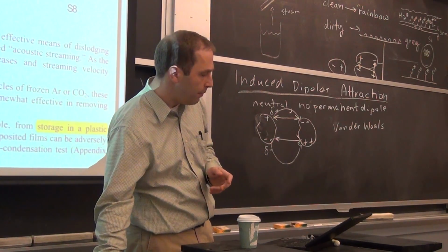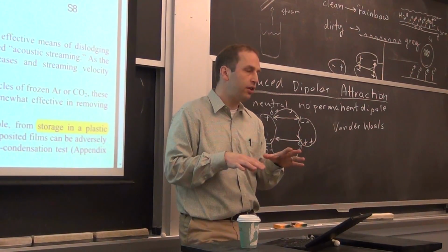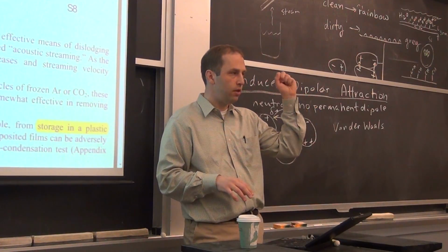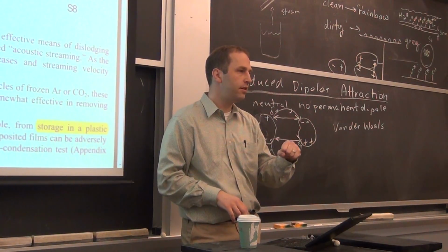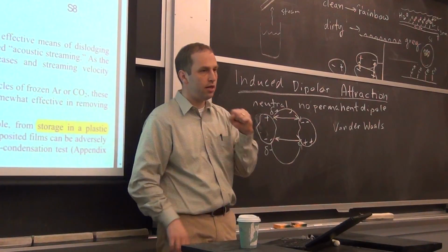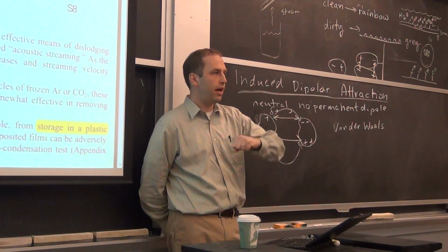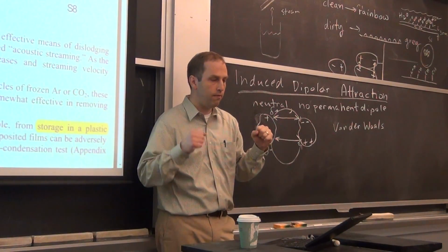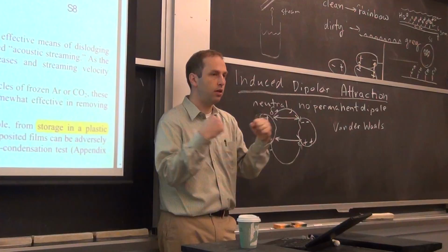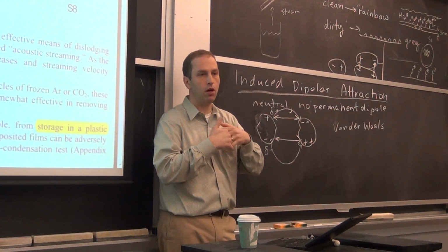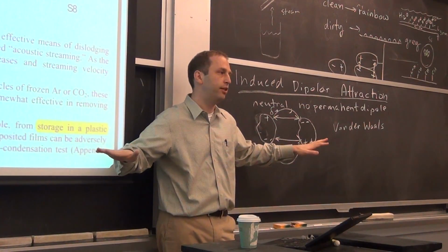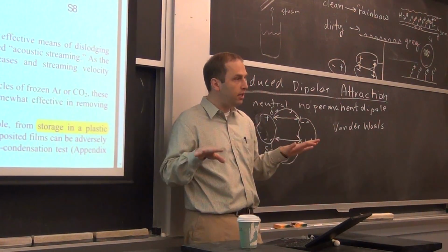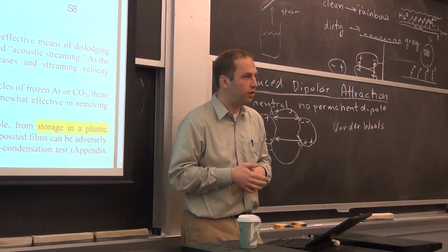The thing to keep in mind is once you've got a clean surface, it's actually not terribly easy to contaminate it. If you have a clean surface and a volatile organic lands on that surface, because the volatile organic is not strongly attracted to the surface, it'll actually with high likelihood come back off. Eventually you get 3 or 4 such molecules that collide, and then they form a network that nucleates basically a contaminating sheet. And so you're safe for probably about 24 hours. If you've got a clean surface, it's going to stay clean for a certain period of time.